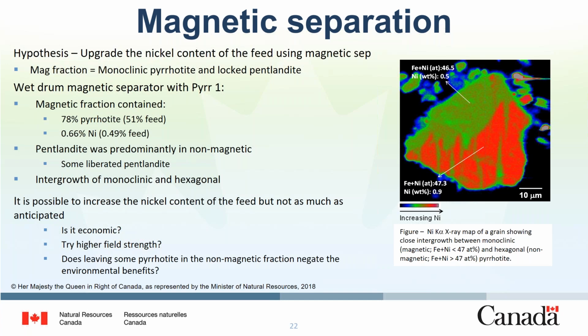We were able to increase the nickel content in the mag fraction, as you can see, but not as much as expected. We characterized the 2 fractions and found several reasons for the lower than expected results. The first one being most of the pentlandite actually reported to the non-mag fraction, indicating that it wasn't locked in pyrrhotite, it was actually free. And second being often the hexagonal and monoclinic pyrrhotite forms were found to be intergrown, and mixing mag and non-mag in the same particle makes magnetic separation significantly less effective.